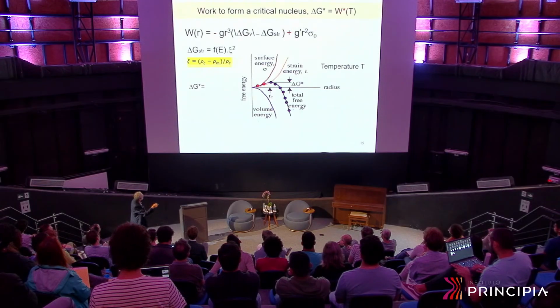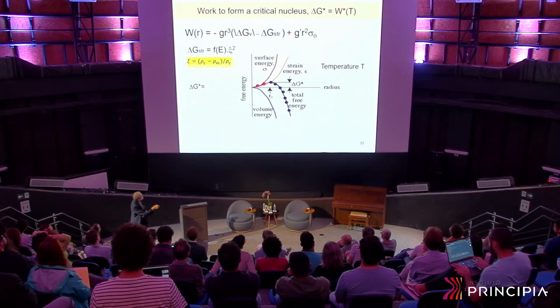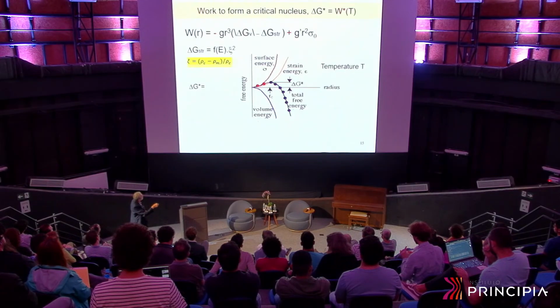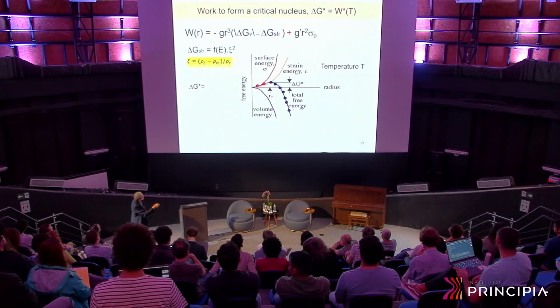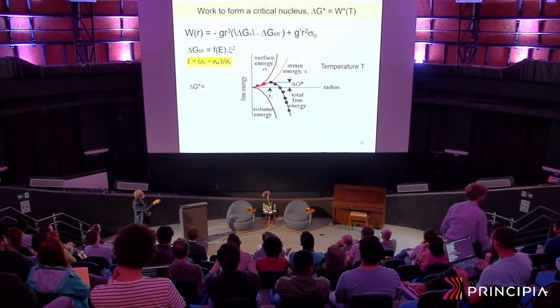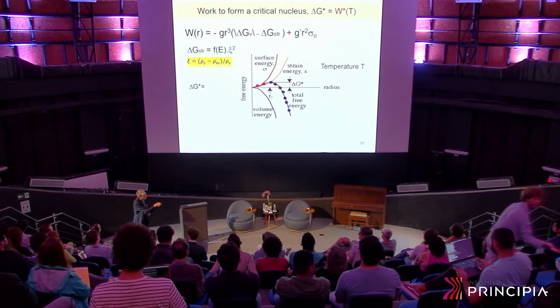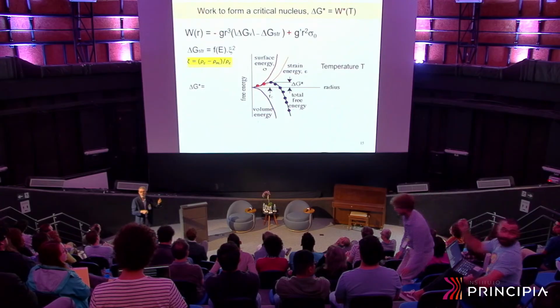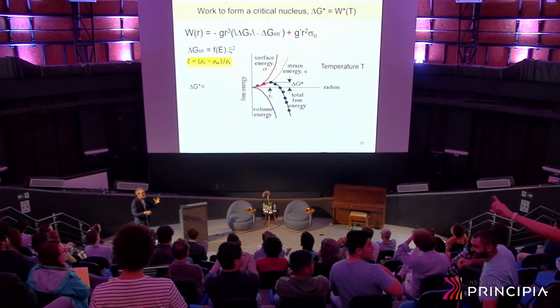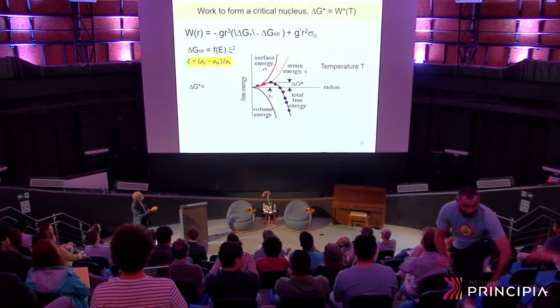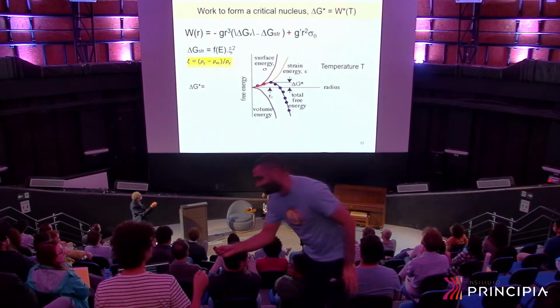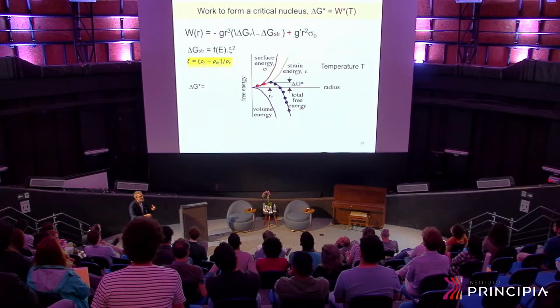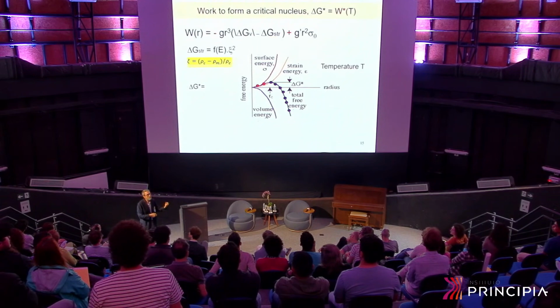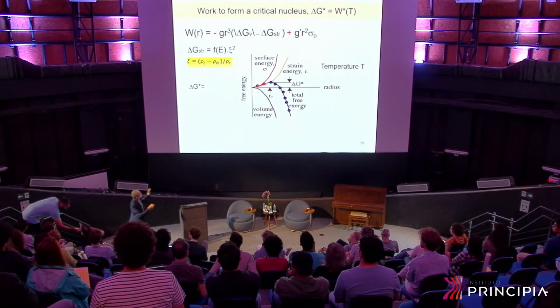If you plot the overall Gibbs free energy versus radius, this is the resulting curve. If the fluctuations are smaller than the critical radius, they will dissolve back. They form and dissolve to decrease the energy. If they're larger than the critical radius, they will grow, and then you count it as a crystalline nucleus. This is a very simple but elegant idea proposed by Gibbs many years ago at a certain temperature. If you change the temperature, you change this curve a little bit, but the same concept applies. Any fluctuation needs to reach a certain critical size to be able to grow. That's the idea.